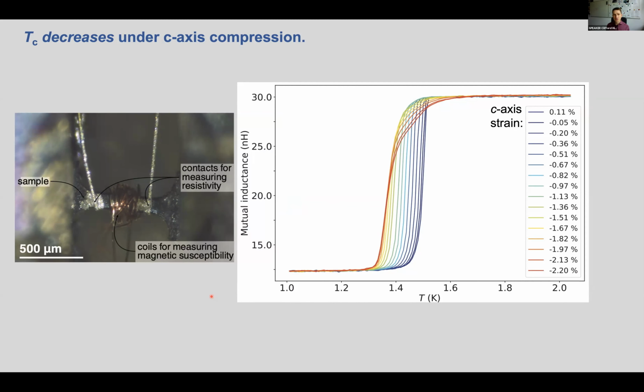Almost certainly there's no motion of defects within the sample. I mean, we apply strain and we go back and we see that the behavior is elastic. If you apply high uniaxial stress to strontium ruthenate at room temperature, you do see introduction of dislocations, and you see motion of those dislocations. It deforms plastically above about 0.2 GPa. So it's crucial here that we're only applying these stresses well below 10 Kelvin. So there's very little thermal energy for motion of defects. I can't tell you for certain that no defects are moving around, but I can tell you for certain that we don't see any large-scale plastic deformation of the sample.